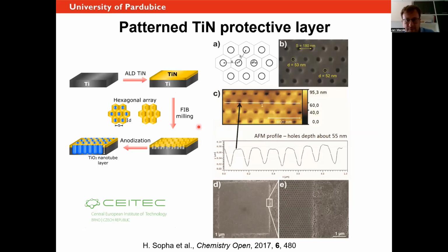What we tried in my team, and I think so far this hasn't been beaten, is to use some kind of protective layer, which we then pattern. So we took titanium, we did titanium nitride coating on it by atomic layer deposition. And we basically created a very thin and very robust, chemically and mechanically robust layer. And then we took focused ion beam and we drilled holes in certain hexagonal arrangement as shown here. We also varied the distance and the diameter of it.